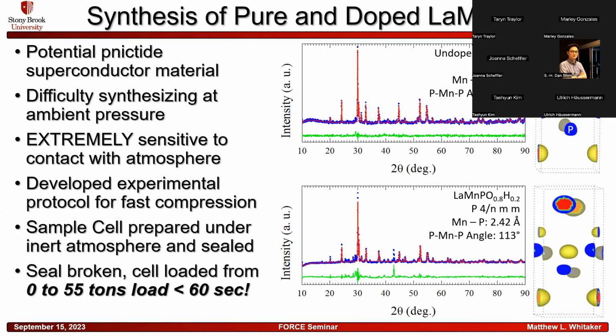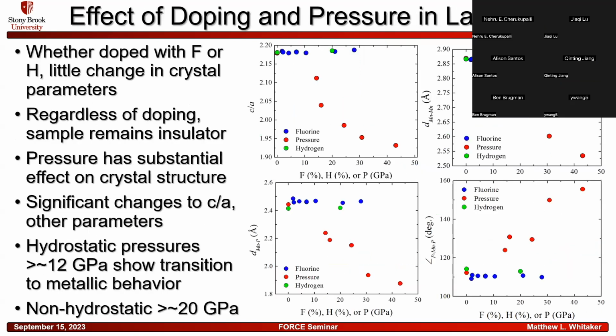We also were able to pull off all of these experiments without ever once breaking a cell assembly, thermocouple or anvil. So I'm very, very pleased about that. One of the things that we found is that whether it's doped with fluorine or hydrogen, there's very little change in the crystal parameters. And regardless of the doping, the sample does remain an insulator.